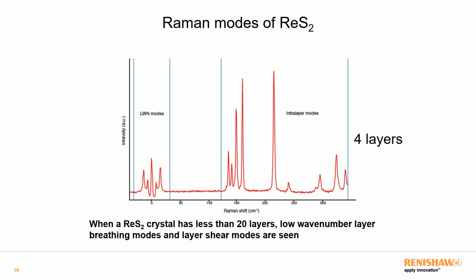And these modes correspond to the number of layers of the material. So as you increasingly add layers to the material, the modes themselves start to become damped, and that changes their energy. So this is an interesting way to identify layer number in 2D materials, and it's something we're going to talk about more in this study a bit later on.